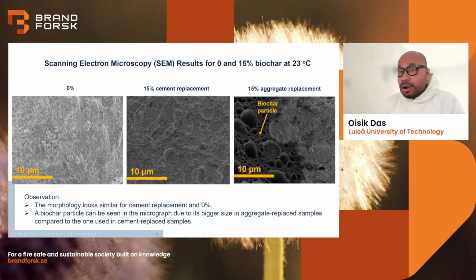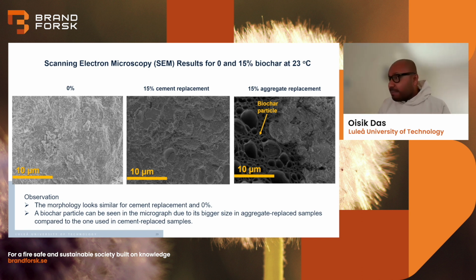So if you look at the standard concrete without any biochar, then concrete where the cement was replaced with 15% biochar and where the aggregate was replaced with 15% biochar, we see that the morphology looks quite similar in all three samples. In the aggregate replaced sample, we see a big biochar particle as it is pointed out by an arrow, the porous structure, and then we have the cement phase and the biochar particle. It is more visible in the aggregate replaced samples because if you remember, the biochar in the aggregate replaced samples was bigger in size, like 3 millimeter. Whereas in the cement replaced sample, the particles were very fine, so it kind of mixed with the entire cement phase. So the biochar in the aggregate replaced sample was more visible in microscopy.